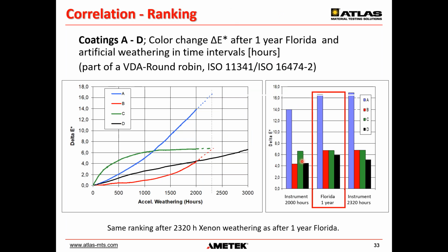However, not all materials behave the same. Not all materials behave linearly. So typically what's happening, and that actually happens very often, is that the ranking is changing during the exposure. Here we have a set of coatings, and ISO 16474-2 would be the corresponding standard today. And they saw that in this set of coatings, the delta E is actually changing the ranking during the exposure